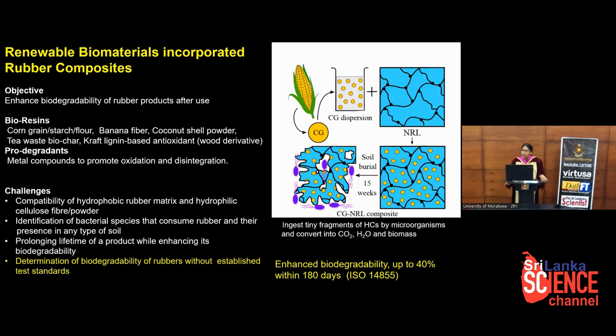Unfortunately, there are no international or national standards to measure the biodegradability of rubbers. We also have to use standards that are established for plastics, and this test is done for composting conditions and for aerobic digestion. Only 40% degradability is obtained within 180 days. But to validate the biodegradability of a product, 90% of the hydrocarbon has to be degraded within 180 days. But that limit is for the plastics and not for the rubbers.